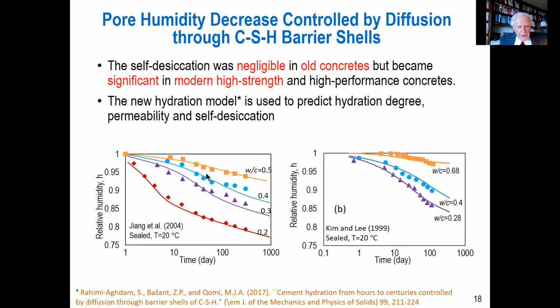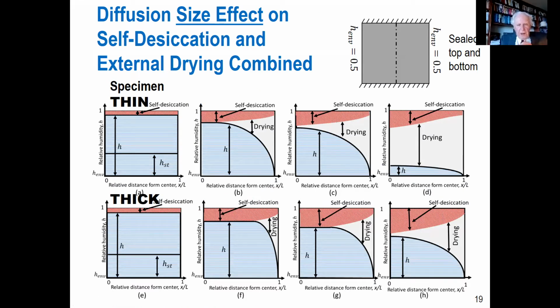So we fit these data here for various water cement ratios, 0.5, 0.4, up to 0.2. So this will be the extreme, you cannot do less. This is actually the minimum required for hydration, 0.2 is the minimum. These are data for another set of water cement ratios. So that's one aspect, self-desiccation. So when the specimen is sealed, the self-desiccation, decrease of humidity will occur below saturation.